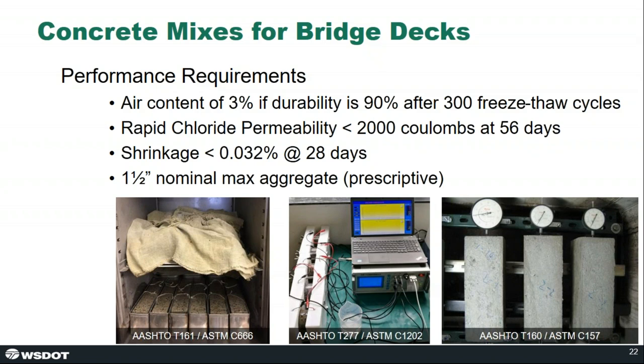And one other requirement I'll throw in there is that we specify an inch and a half nominal max aggregate in our bridge decks. The larger aggregate is helpful in reducing the paste content of the mix and therefore the shrinkage in the mix. So in the past, we had seen maybe 3/4 inch nominal max aggregate mixes. So we're getting larger rock. This isn't particularly a performance spec, but we did want to set an upper bound here too, because we didn't necessarily want a contractor proposing a 2-inch aggregate in order to limit shrinkage when we were fairly certain that we would have placement issues with a mix that had 2-inch aggregate in it, given the tight clearances and tight spacing oftentimes seen in our bridge decks.